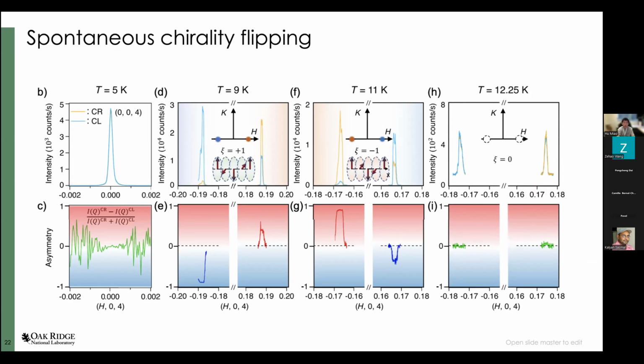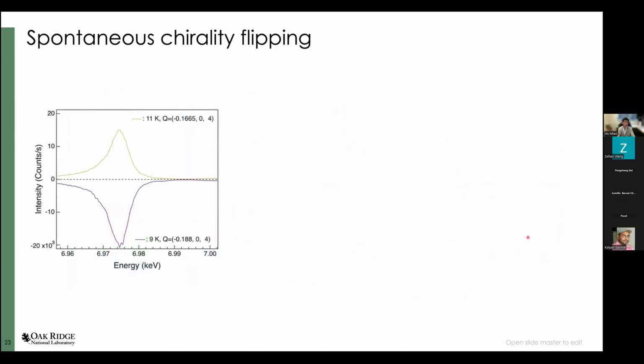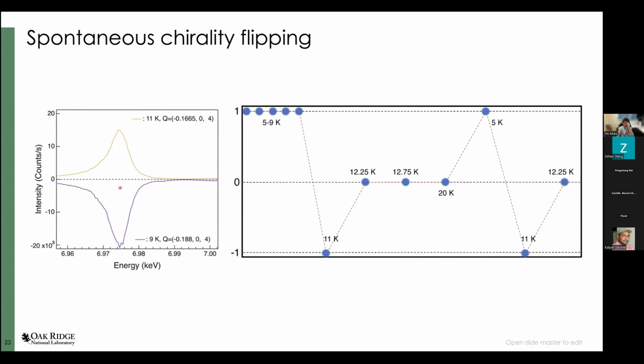And we can also check the energy dependence. And here we only observe the circular dichroism on resonance. That once again confirms the circular dichroism is coming from the magnetic order itself. Quite interestingly, we can ask, what happens if we warm up and cool down? Does the chirality remain the same or would the chirality be different? So here we show the hysteresis scan.